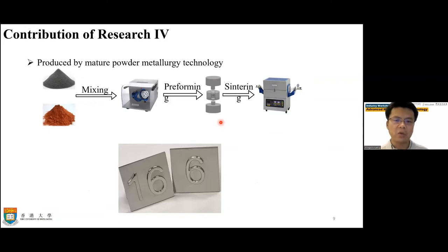So basically what we are doing, we try to make a demonstration of whether or not our stainless steel can be used in a daily life product, like lift buttons or in other applications. So we made two lift buttons using our stainless steel based on a powder metallurgy technique. We can also do conventional casting, but conventional casting may have some technical challenges to be solved. We are working on that now, to solve the technical challenges of using conventional casting to contain such high copper content. But if we use powder metallurgy, it's quite easy. And powder metallurgy is a well established technology that is easily available. So by powder metallurgy and dual sintering, we can now make these products, which we have already done.